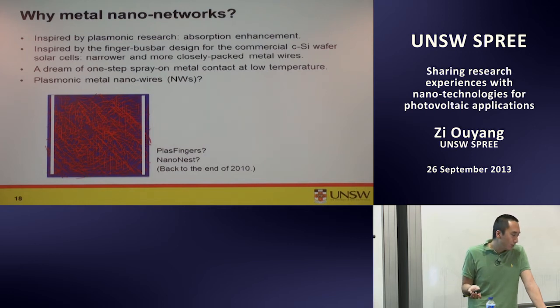So naturally, you want to think, why don't we just make some nanowires which can be conductive, used as an electrode, and have the light absorption boost at the same time. So I was very excited, like 2-3 years ago. And so obviously, you always have a dream of one-step spray on metal contact at low temperature, which is fundamentally possible with this kind of structure. So I was very excited.